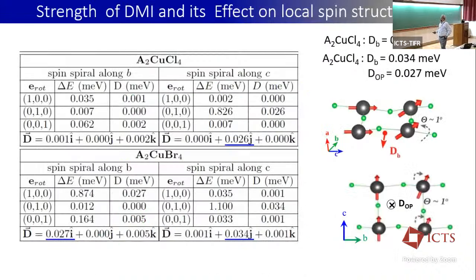If you look at the total calculation for the chlorine, we get a sizable D of 0.026 when our spin spiral is along the C-axis. And for the bromine case, we get two sizable D values, when the spin spiral is along B and along C. So what does it do? This is a D along the B direction. So what will happen if your spins are in the BC plane, and as I told you, these are quasi-2D magnets, it will try to tilt towards the AC plane, because wherever the D vector is, it will cant the spins to a perpendicular plane. So this is what I have shown, a little canting here because of this.